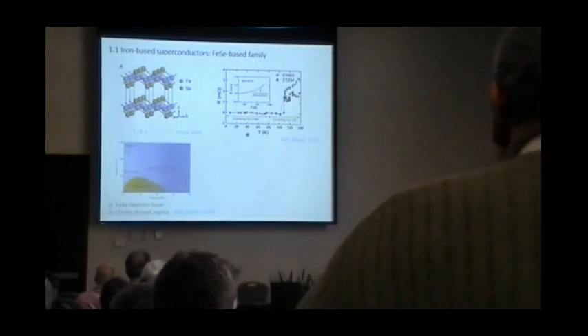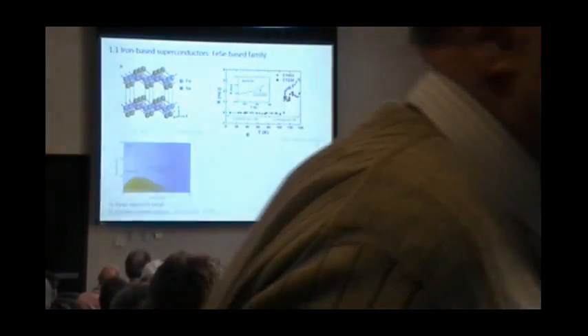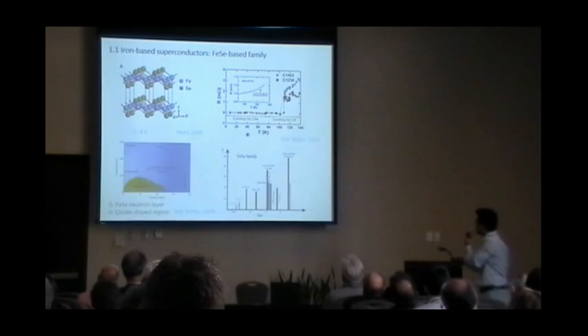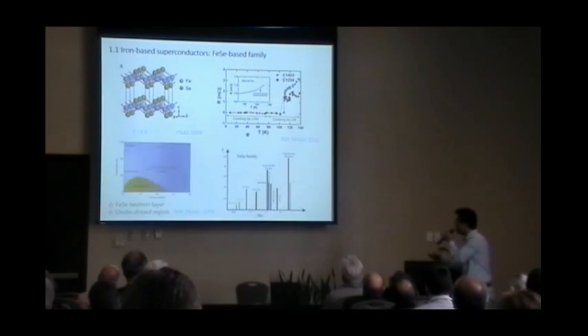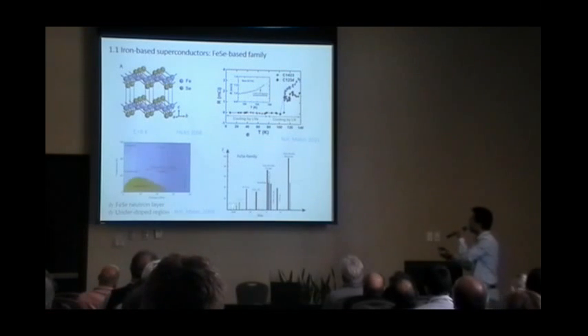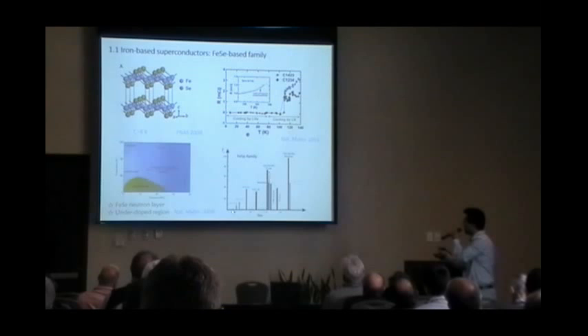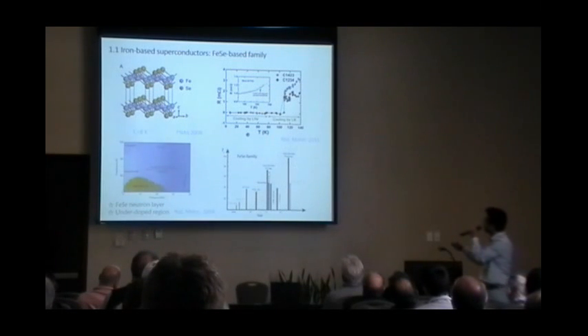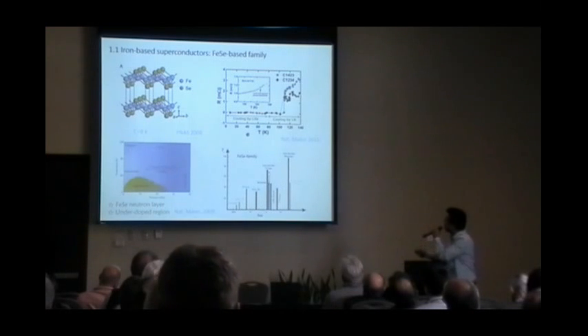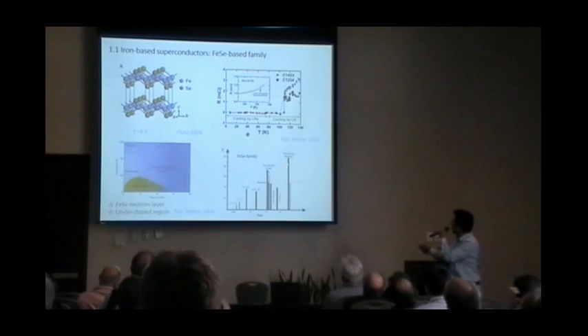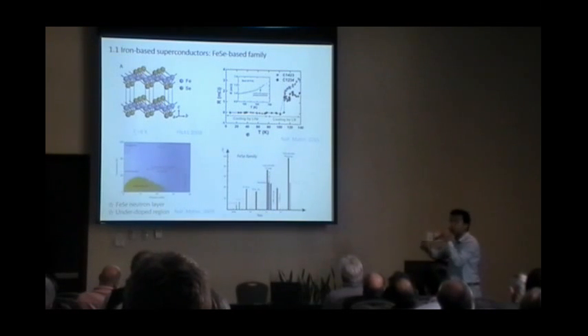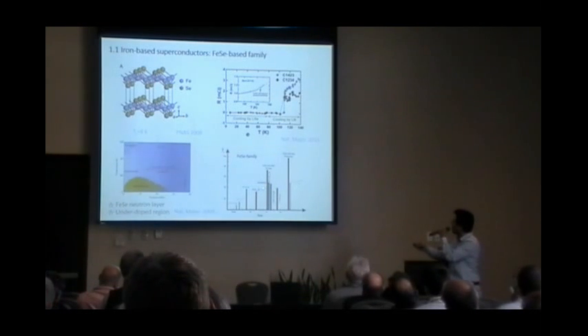This one is a pretty new result: one thin film layer, just one thin film layer showing here. The TC is around 100K. This is very huge. This is a very simple diagram showing how the TC of the iron selenide family changed. You can see from 2008, it was only 8K, and now it's already showing 100K. But note that the very high TC comes from the thin film, not the bulk. The highest TC of the bulk sample is around 50K.